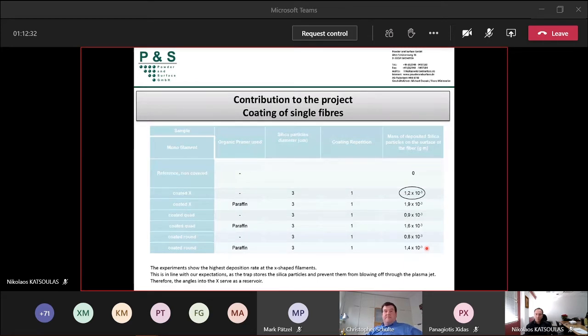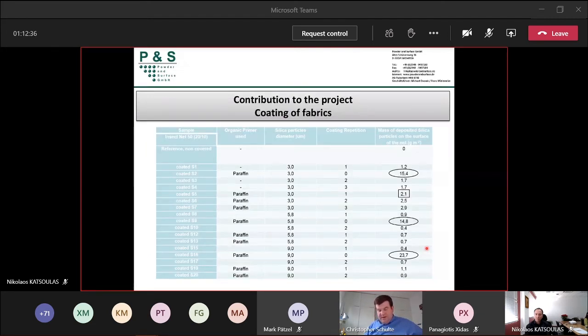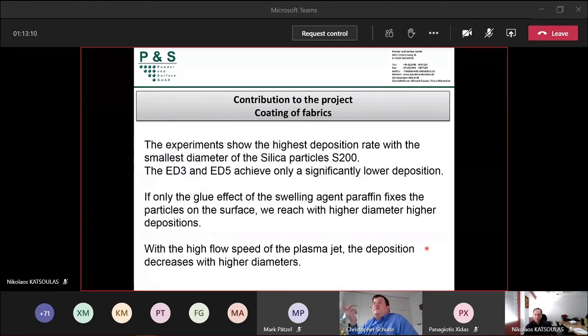The next big task was to find out which particle size and which coating parameters deliver the best deposition results. We coated for this a mesh 50 fabric with three different particle sizes and with and without swelling agents. And of course, we took different numbers of repetitions. And as you can see on the next page, please, it turned out that, first of all, the highest deposition rate, as I mentioned before, was with the smallest diameter of the silica particles. This is based on this blow effect of the plasma jet. And the bigger diameters, ED3 and ED5, achieve only a significantly lower deposition without a swelling agent.